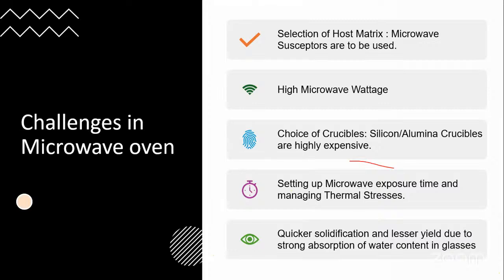So I have to go with a silica crucible or alumina crucible, which is very expensive. For example, in the melt quench technique, I can just pay nearly 70 rupees per crucible and get my sample done, whereas here I have to spend nearly 400 rupees per crucible, which is very expensive. And further, the exposure time and managing the thermal stresses depend on the microwave exposure, how it is susceptible, and where it is placed. All these things play a very important role.